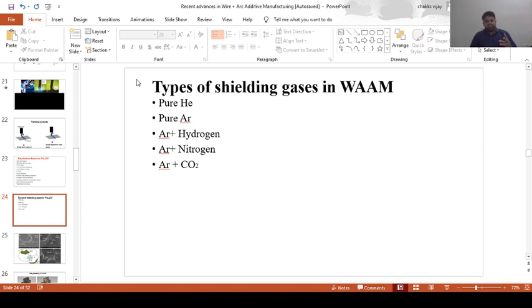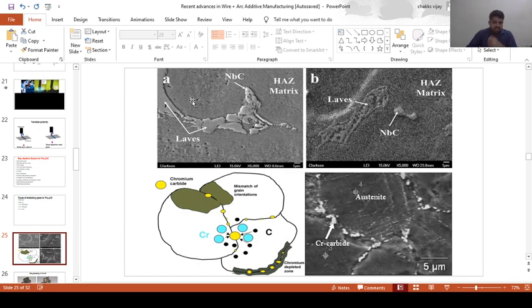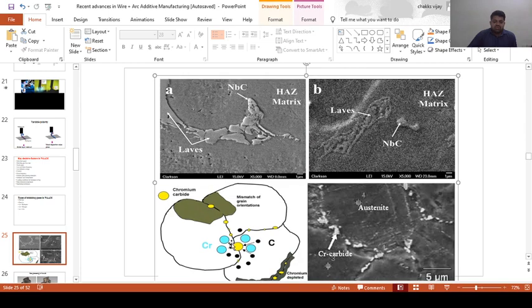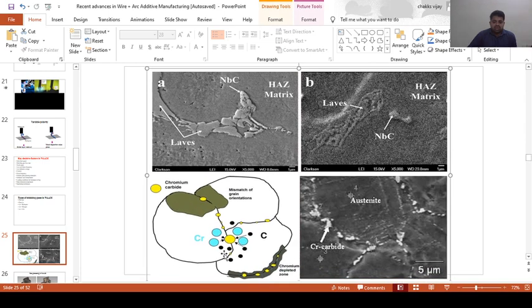Okay, so this carbon is a highly reactive material which will react with the chromium, or else with molybdenum, and form chromium carbide or molybdenum carbide. So let's see here. Here you can see the metallographic structure. Especially in a scanning electron microscope, we can observe each and every single grain boundary. Inside is a grain, and the outer area is the grain boundary.